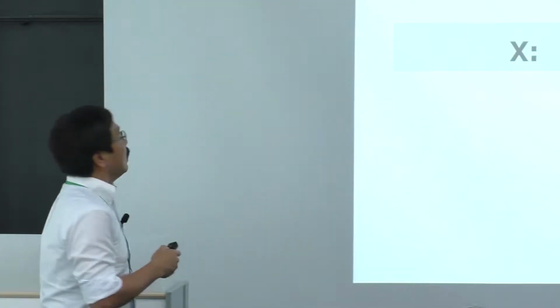Of course, they have disadvantages. The biggest disadvantage of alpha iron is rust - namely, alpha iron is very easy to oxidize in air. This tendency to oxidize is especially prominent for nanoparticles, because they have large specific surface areas.